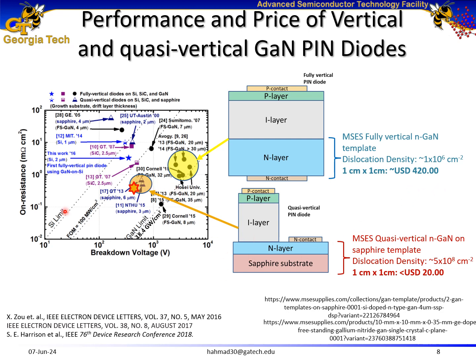I've shown here in this plot what I'm going to show later in my results. Our gallium nitride based pin diode, represented by the hexagonal star here in the plot, is comparable to the state of the art MOCVD best quasi-vertical gallium nitride pin diodes. And this is the only MBE based pin diode which is comparable to the state of the art pin diodes. And we are confident that we can further exceed the performance of these pin diodes.